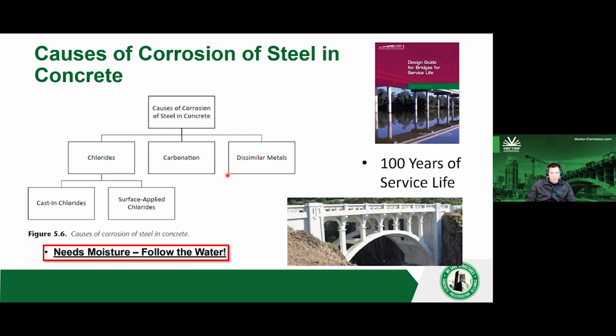The next one here, carbonation. Carbon dioxide and carbon monoxide, just from the atmosphere, over time will leach through that concrete and react with the free lime, and the free lime is what gives the alkalinity. So by reducing that, alkalinity is also reduced, and corrosion can initiate due to that. And in some cases, both of these, chlorides and carbonation, will be an underlying cause for corrosion. This is typically found in older structures, carbonation, or those with low concrete cover. But just know, both are causes.